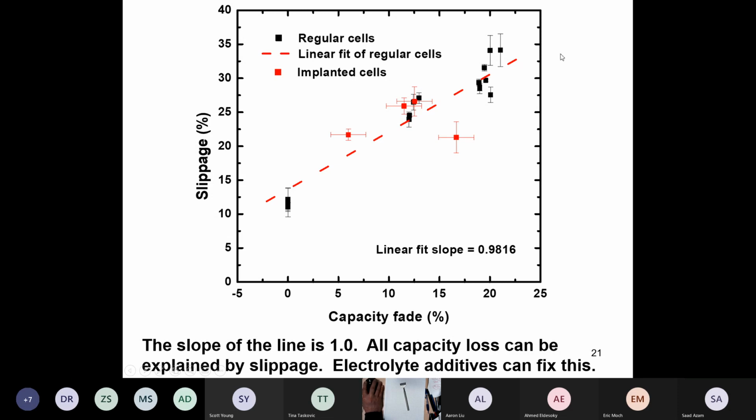So you learn when you do this work that the problem in these cells is the electrolyte. You have to improve the electrolyte through better additives, or maybe you need coatings on the electrode materials, but your electrode design is fine. You have enough conducting carbon in there, it's been calendared properly, you're not losing active mass.